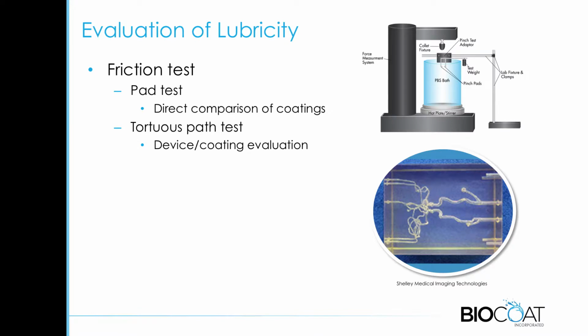but then if you want to think about it for that device, getting through and simulating what's going into the body, you'd have what I call a tortuous path test, which is a simulation of the anatomy in the body, for example, a neurovascular anatomy. That looks at both the device and the coating together, and you can evaluate that. In seeing how well that ease of insertion goes, you can measure the force it takes to apply that. That goes for the initial friction. Then if you're doing multiple cycles on that, you can look at the durability for that device.